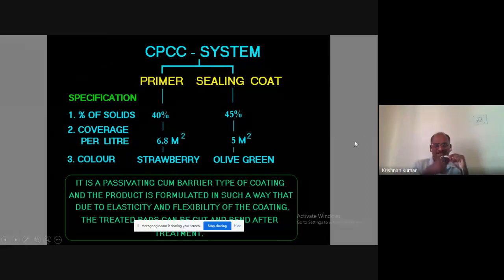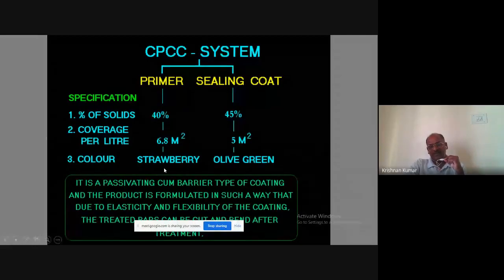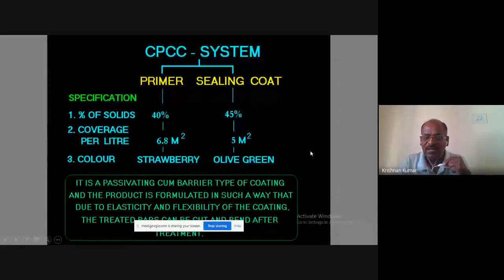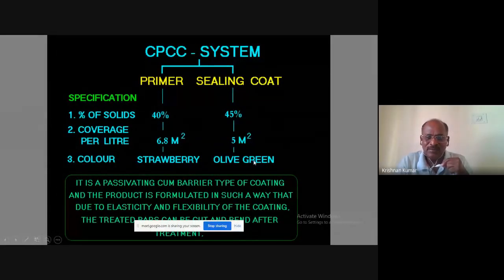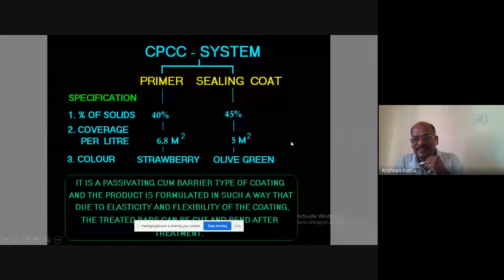So what is the CPCC coating system? It has a two-coat system, primer and sealing coat. We can apply it by spray, by brush, or we can dip. It is a fast curing type. So the primer you can apply on the prepared surface of the steel reinforcement, and after that you can apply a sealing coat.